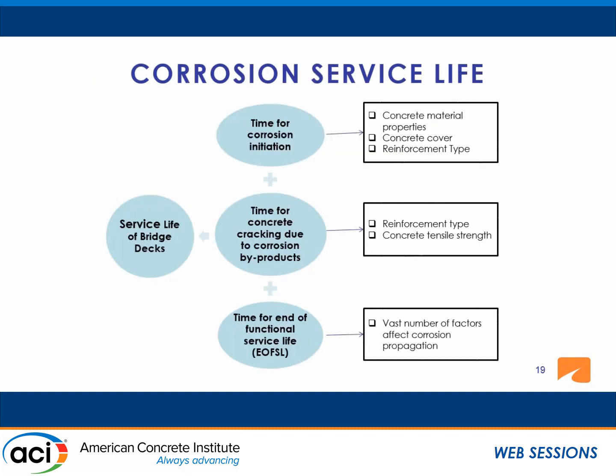So for service life modeling purposes, we divide these into three stages. The first stage is the time for corrosion initiation, which depends on the concrete material itself, the concrete cover depth, and the type of reinforcement. And the second stage is the time for concrete to crack once the corrosion has initiated. And this depends on the concrete tensile strength and the reinforcement type, because different reinforcement types have different byproducts. And the last stage is the time for end of functional service life, which is also called the propagation phase. A vast number of factors can come into play, making this extremely hard to model.